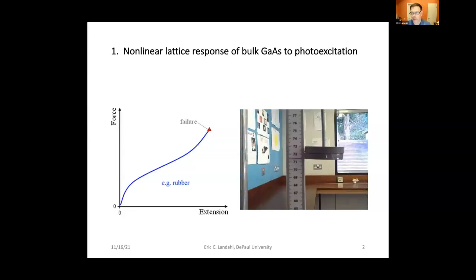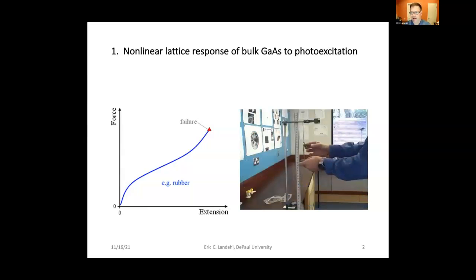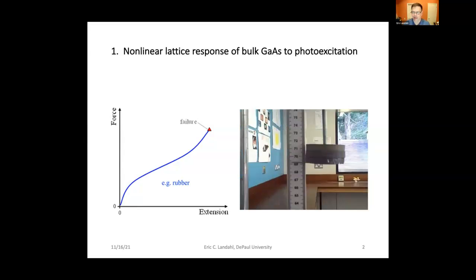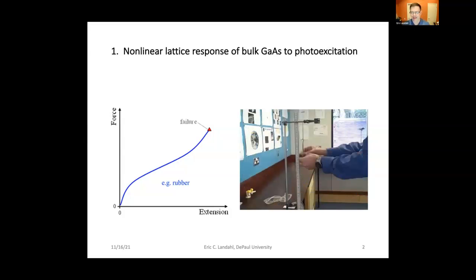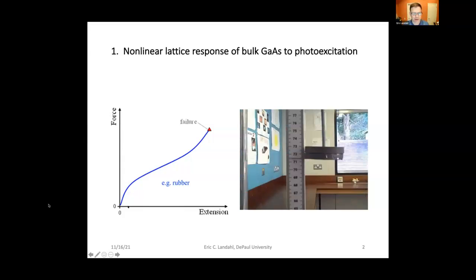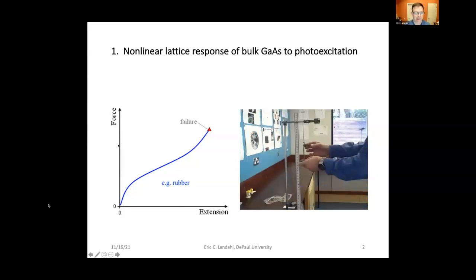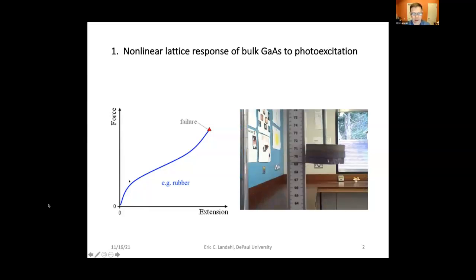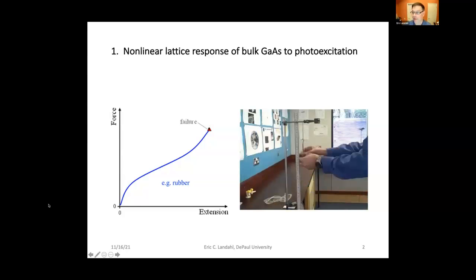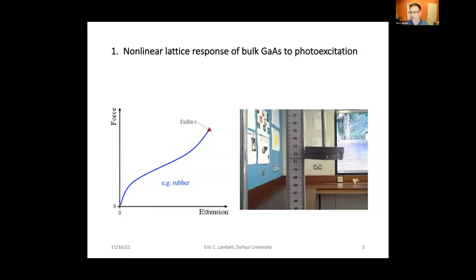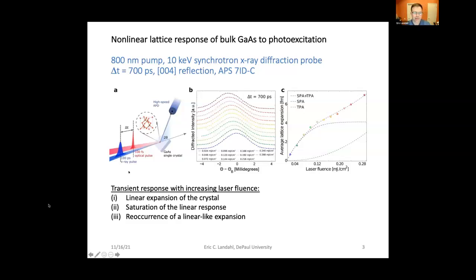So this is sort of what I had in mind when we designed the experiment to understand how any semiconductor would respond to photoexcitation, which was gallium arsenide in particular, because we knew it would exhibit many nonlinear properties like the elastic band shown here. And we wanted to trace out a curve where we would measure the extension or the lattice expansion based on the amount of laser light we put into it, and fully expected to see a linear region and a region that is not linear. And I'll show you how we did this, and that it comes from the presence of electrons. It's fairly standard at this point in time resolved X-ray diffraction setup.